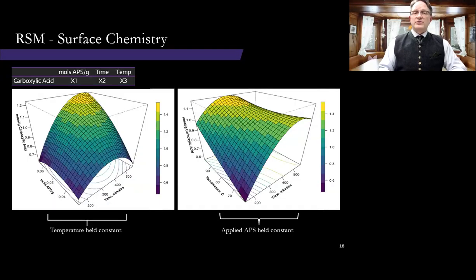Now I'll get into a discussion and summarize my results, starting with surface chemistry. A statistical analysis revealed that the applied concentration of ammonium persulfate had the greatest effect, followed by time and followed by temperature. If you look at the response surface that was generated on the left here, as you increase applied chemistry or increase time, the surface charge on the surface of the fiber increases accordingly. With ammonium persulfate held constant on this right one, same thing, just adjusting temperature and time, you can see how the surface charge responds accordingly.